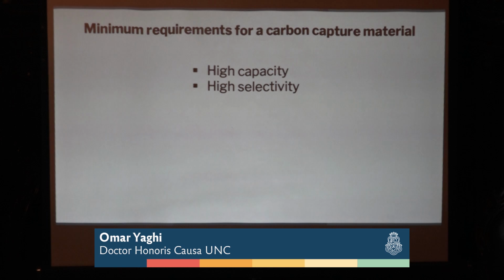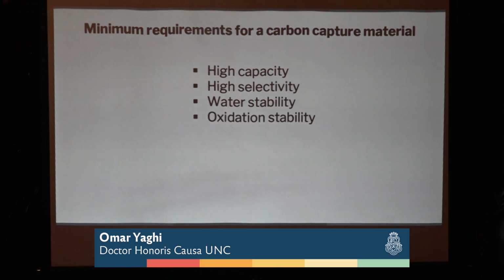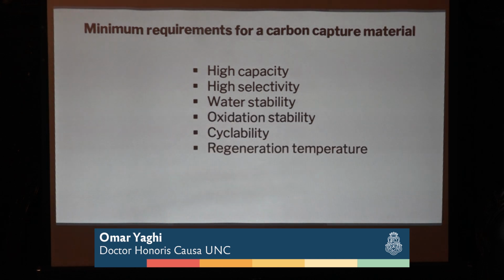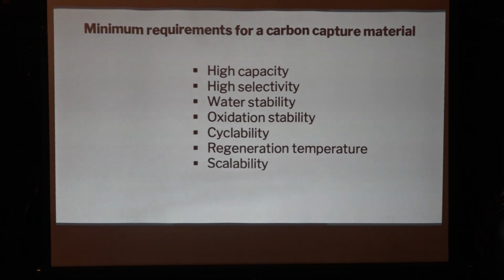You need high selectivity. You need the material to be functionalized in a way that can pluck CO2 out of the air, leaving everything else behind. Otherwise, the other gases will occupy space inside your porous materials that will not be efficient. It needs to be water stable. It needs to be oxidatively stable. It needs to have cyclability. It needs to have low regeneration temperature, and it needs to be scalable to multi-ton scale.